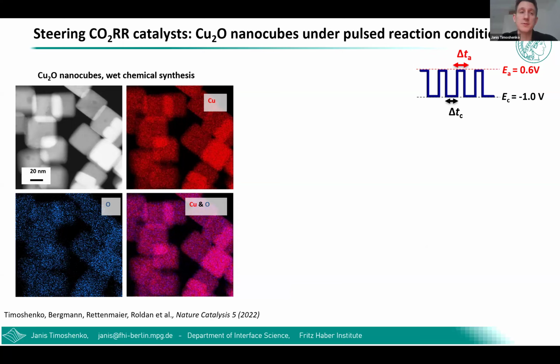So normally, when you're running the CO2 electroreduction reaction, you're applying a static negative potential, which reduces your oxide nanocubes to some metallic copper state. And this is basically the end of your story if you do it under stationary reaction conditions. However, if you periodically interrupt your negative applied potential with short pulses of more positive potential, you can tune the oxidation state of your catalyst and play around with the surface structure of the catalyst which you obtain.